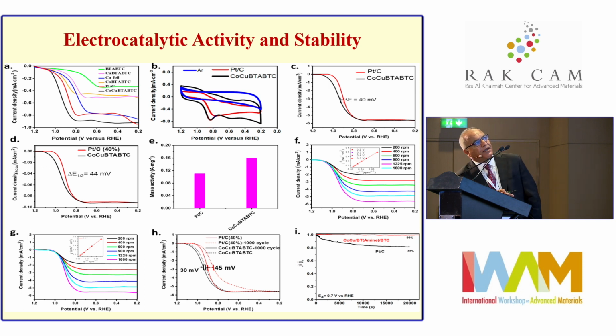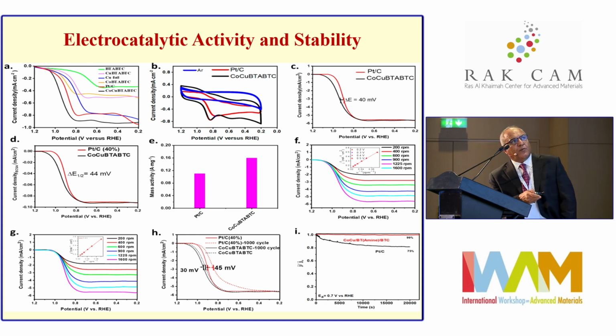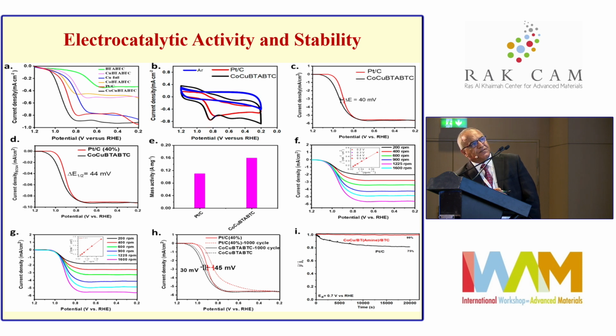In the cyclic voltammetry here, you can see also a well-defined cathodic peak for the black cycle, for the bimetallic MOF, and it's significantly higher than the platinum carbon one, which is in red here. Actually also the current density, but this one was done at 0 rotation, 0 RPM. The measurements here on the right are done at 1600 RPM, which is standard, recommended by DOE for these measurements. And again, we see a significant shift of 40 millivolts toward higher potential for the cobalt copper bimetallic compared to the platinum carbon. You can look also at the mass activity, current per mass. As you see, the bimetallic has a much higher activity than the platinum carbon.